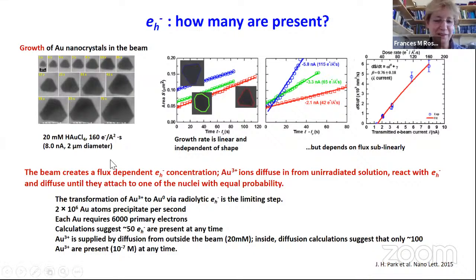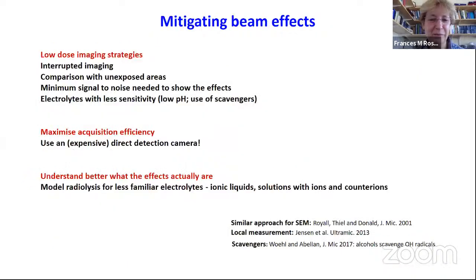And if we do all the calculations, we can find that it takes about 6,000 primary electrons to reduce each gold ion into a gold atom. And there's of the order of 50 hydrated electrons present at any time doing this job. They're created and destroyed very, very quickly, but this is the equilibrium number. Okay, so that's a fun thing, and it's a little bit off the point, but it's just to show that you can get some understanding of what's going on, and it's all consistent with the radiolysis calculations.